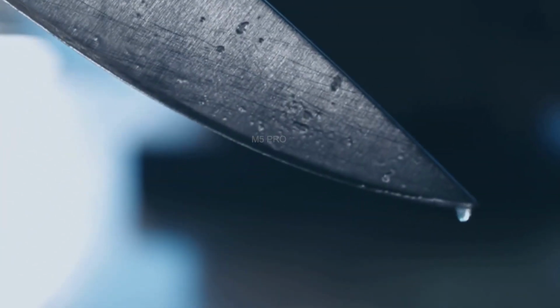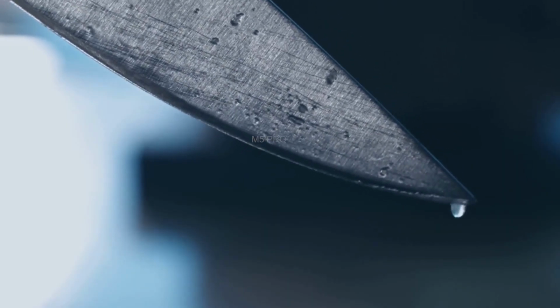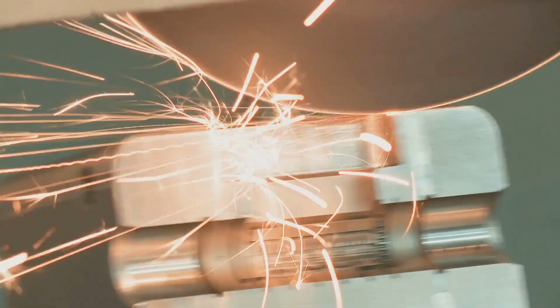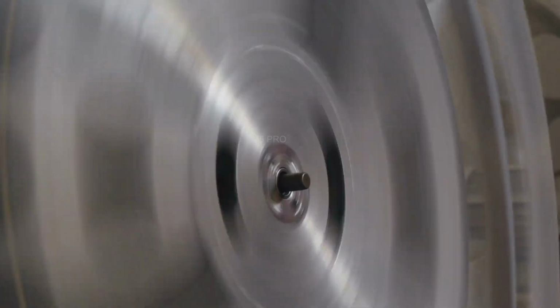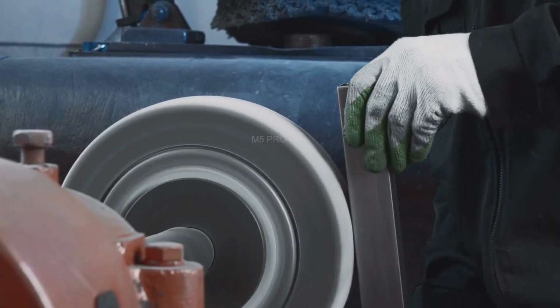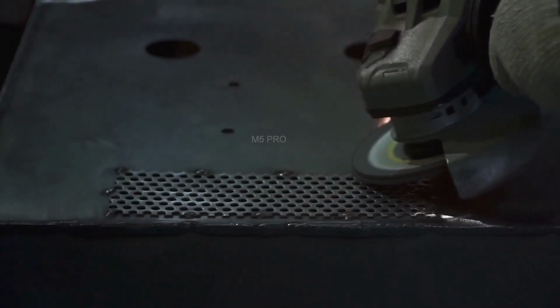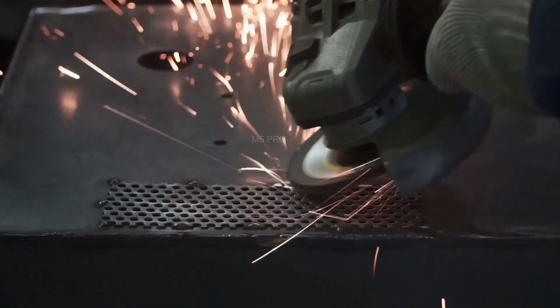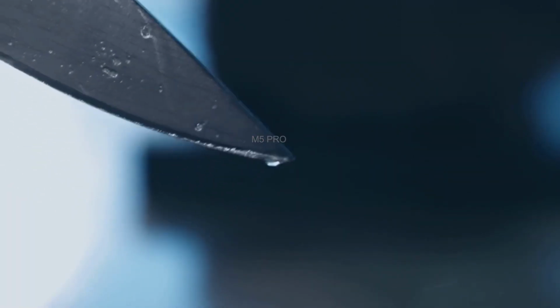For a standard satin finish, we might stop after a few finer belts. For a more polished finish, for a mirror finish, the blade would continue to even finer belts and then to buffing wheels, cloth wheels, felt wheels, wheels loaded with polishing compounds. This final buffing step doesn't remove any significant amount of steel. It smooths the surface on a microscopic level, creating a beautiful, reflective shine.